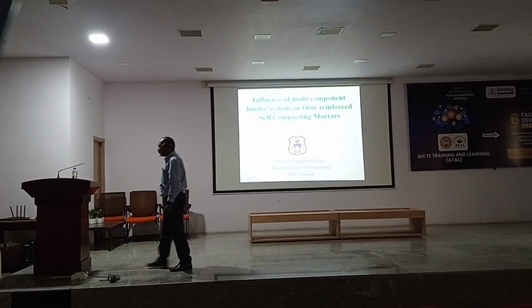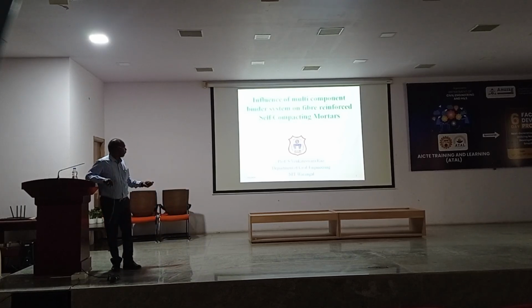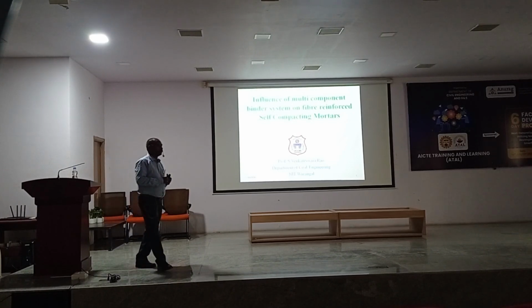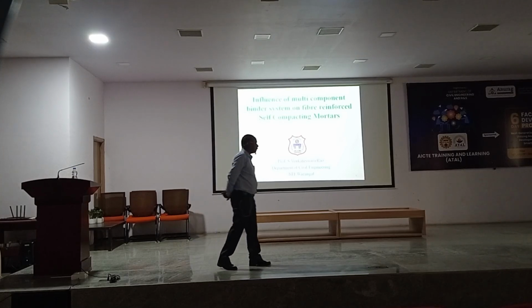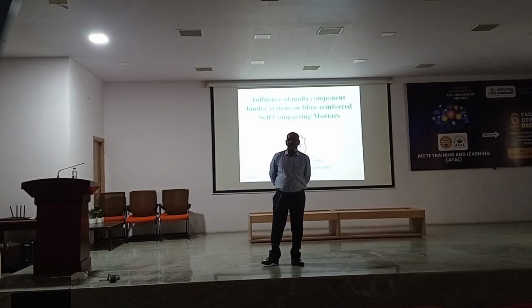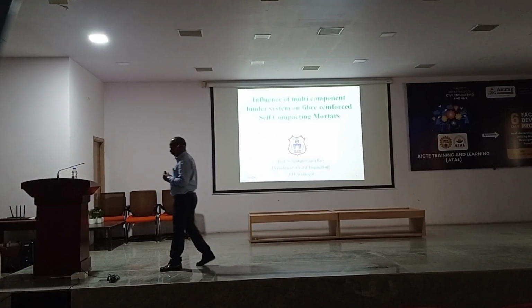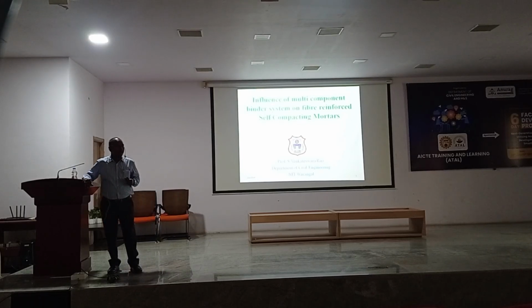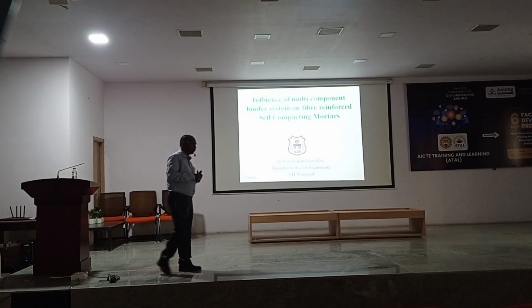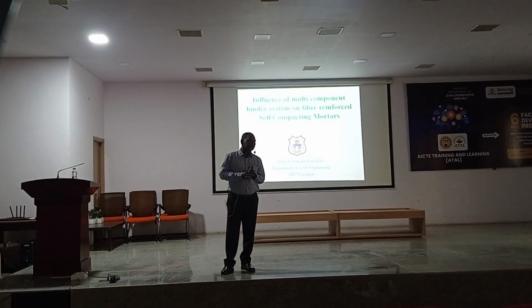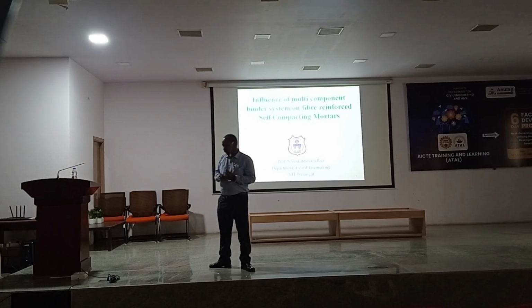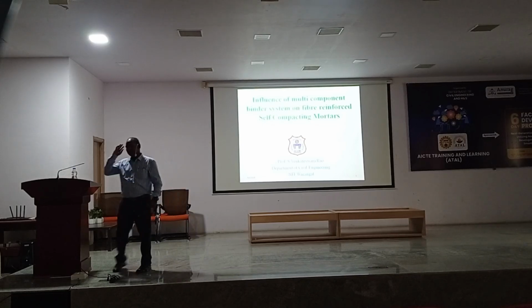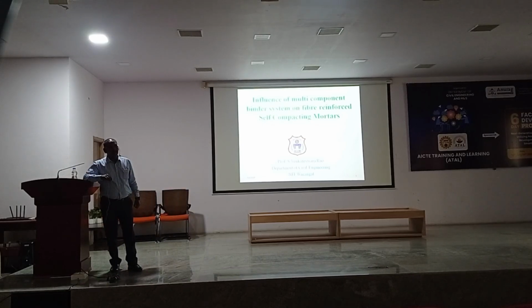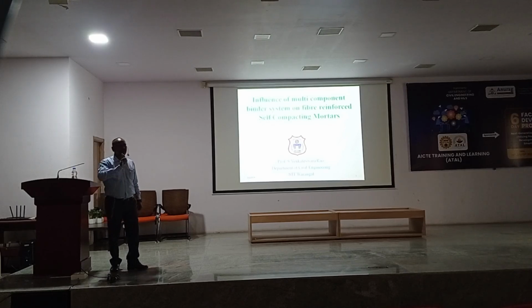What is the influence of this multi-component binder system in the development of self-compacting mortars with fiber reinforcement? What is the application of this fiber reinforcement in self-compacting mortars? What is the use of fibers in the concrete? Residual strength increase, what else? It will arrest the cracks. It will reduce the micro cracks. Micro cracks become macro cracks. If you add the fibers into the concrete, the density of the cracks is increased, but the crack length and crack depth are less compared to that without the fibers.